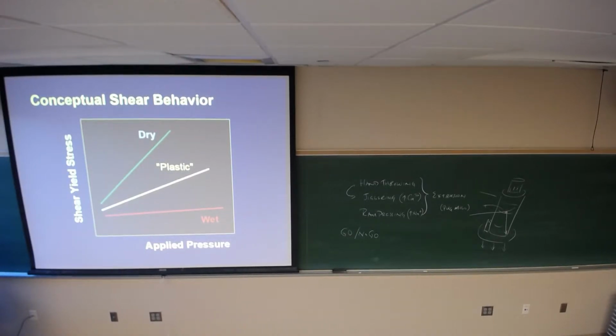Dry is true. So what happens is if you're partially saturated, right, you apply load, what you do is you increase the force and therefore you increase the friction between the particles, right, and that increases the drag on the system. So it's really great for evaluating bodies which are partially saturated because you can actually see what that friction looks like. And we looked at a lot of samples. There's a whole bunch of senior theses that were done this way, and at least 3 master's theses that were done looking at plasticity. We learned a lot. It was good, but it turns out to be wrong. This is really entertaining.